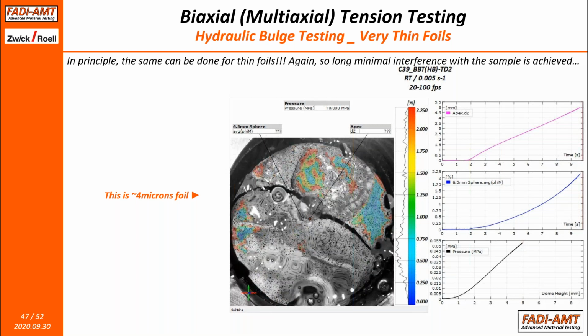You mustn't forget that DIC always requires painting. So imagine a 4-micron foil. When you apply a layer of paint, you're technically interfering with the material. So this has to be checked. And if it can be done with other extensometers without applying anything to the sample, to preserve the sample, then that's fantastic. If not, in this particular case, this is a copper foil, so it's very shiny, very smooth, very nice. There are no contrasts, so applying adhesive tapes, basically markers, for a laser extensometer to follow is really difficult, if not impossible.